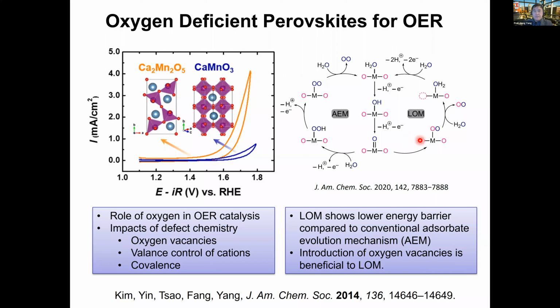So by having this mobile oxygen, the quantum simulation result based on the AEM system typically predicts an OER overpotential of around 300 millivolts, and it could be even further reduced, which has been observed quite well since maybe a decade or two ago. Now we have a theory that contributes to the understanding of this phenomenon.